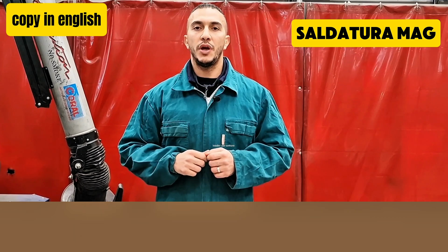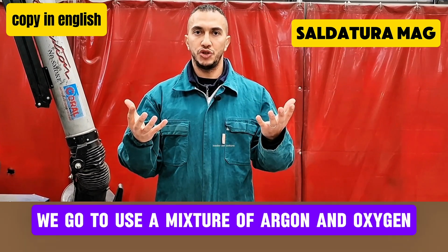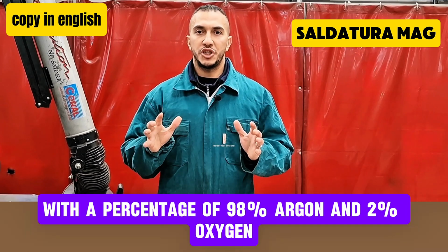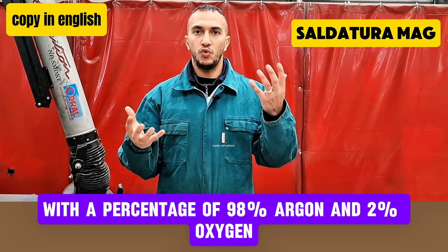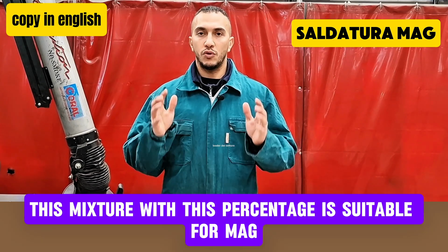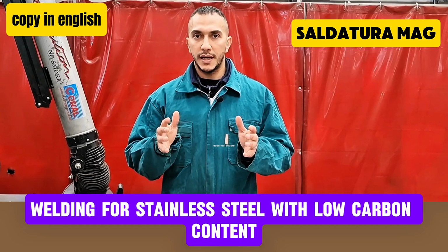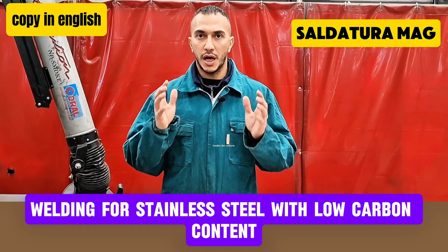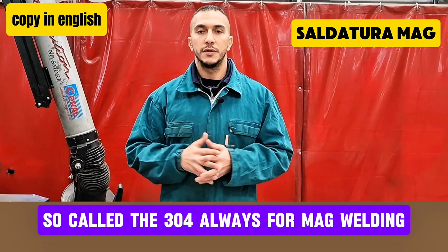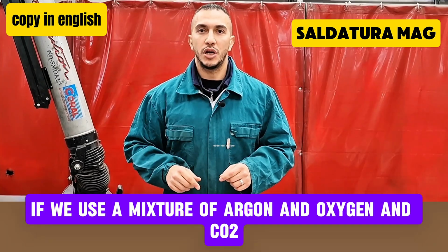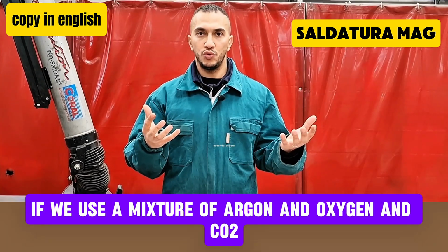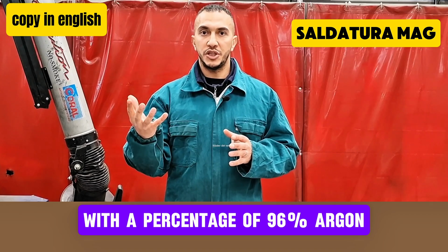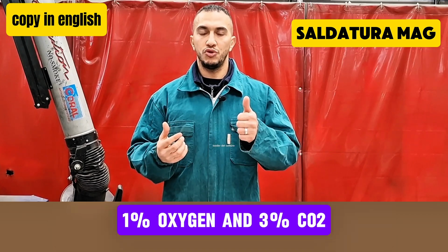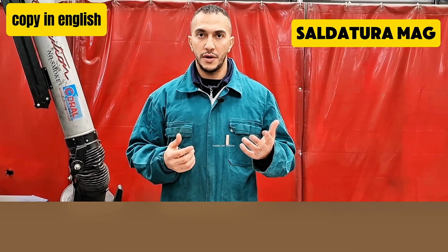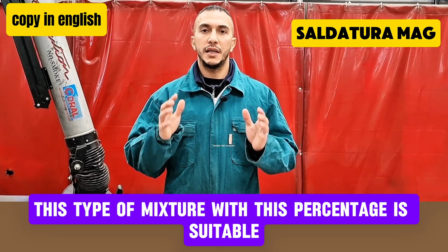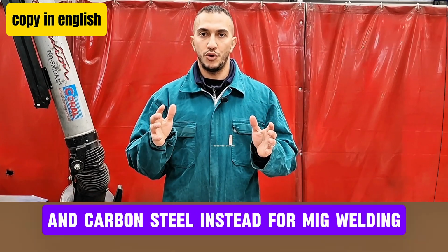If we use a mixture of argon and oxygen, formulated O2, with a percentage of 98% argon and 2% oxygen, this mixture is suitable for MAG welding of stainless steel with low carbon content, so-called 304, always for MAG welding. If we use a mixture of argon, oxygen and CO2 with a percentage of 96% argon, 1% oxygen and 3% CO2, this type of mixture is suitable for welding stainless steel and carbon steel.